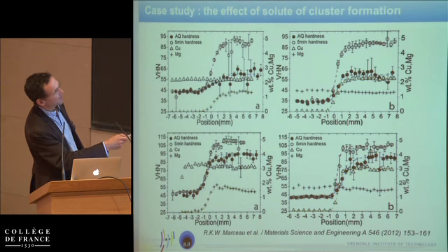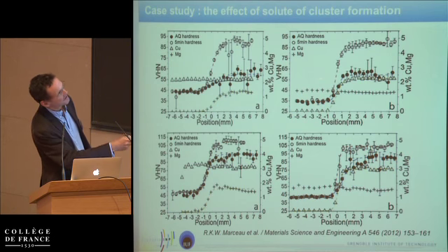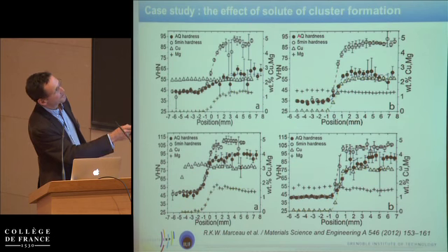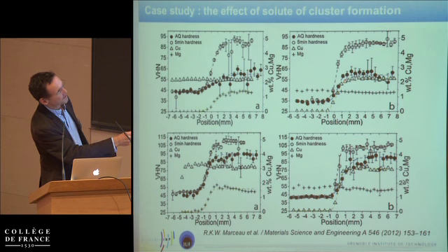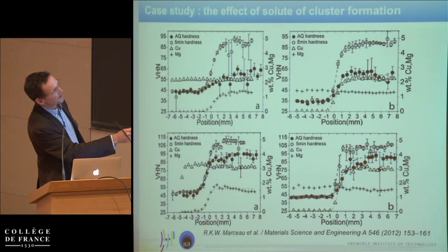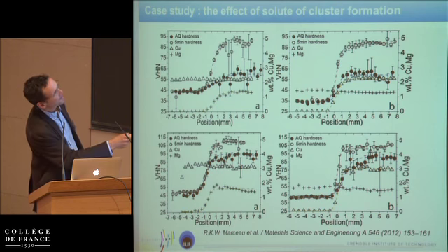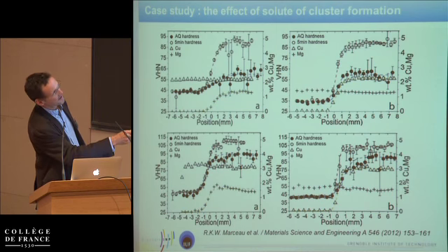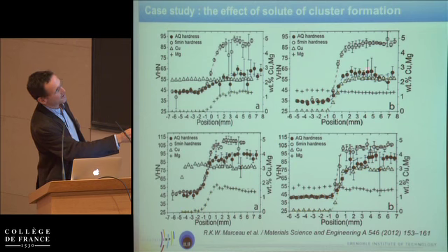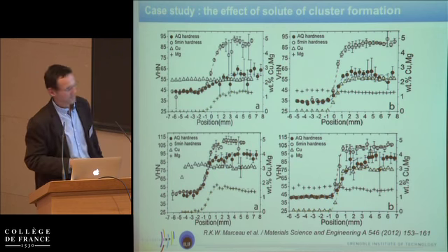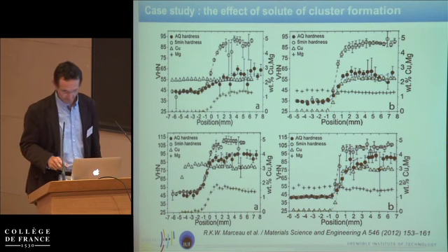Well, let's take one example here. Magnesium is constant. Copper here in triangles is evolving between 0 and 2%. This is as quench hardness, so it's quite soft. It increases as a function of the concentration in copper. And then this is after rapid hardening, so it's 5 minutes at 150 degrees, I believe. And then on the soft side, you have no rapid hardening, so the hardness stays absolutely constant. On the hard part, you get a substantial hardening, and then you can study the effect of composition on this behavior. So, well, these are the kinds of things you can do.